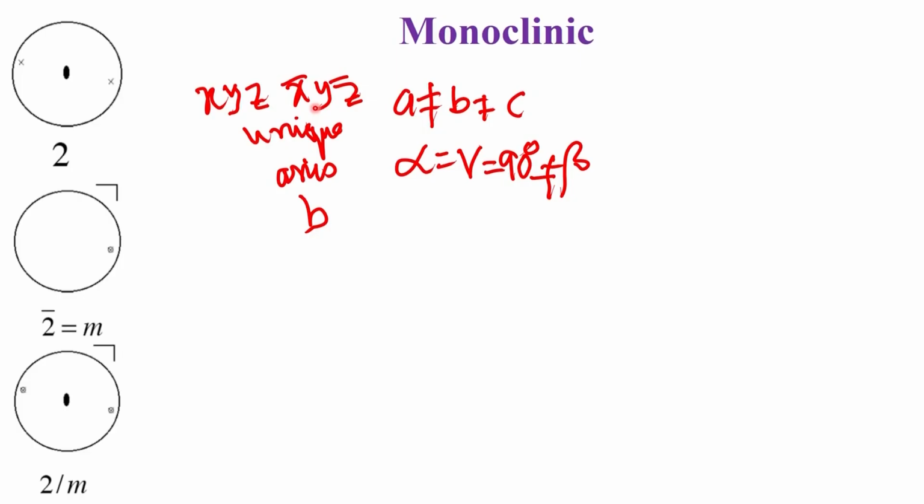So, overall, the volume of the unit cell, we have not defined that yet. So, the volume of the unit cell will be defined now. Of course, there are two possibilities for the unit cell. So, let us first define the unit cell possibilities. The unit cells can be a primitive lattice as well as a C centered lattice. So, the space group can be P2 as well as C2.